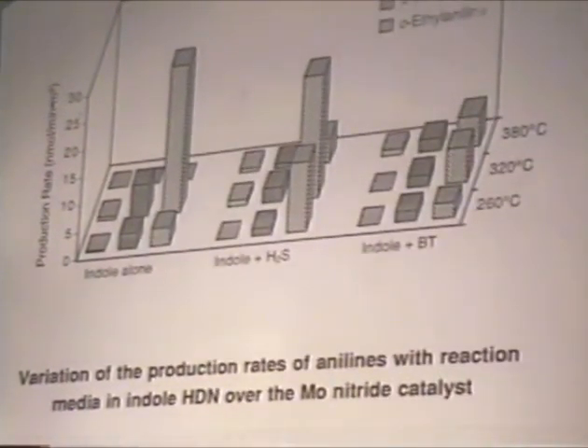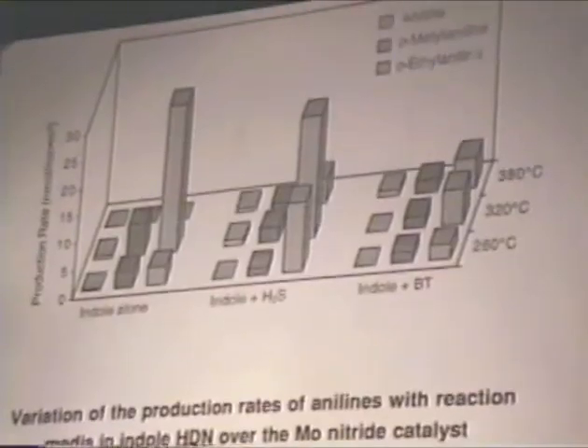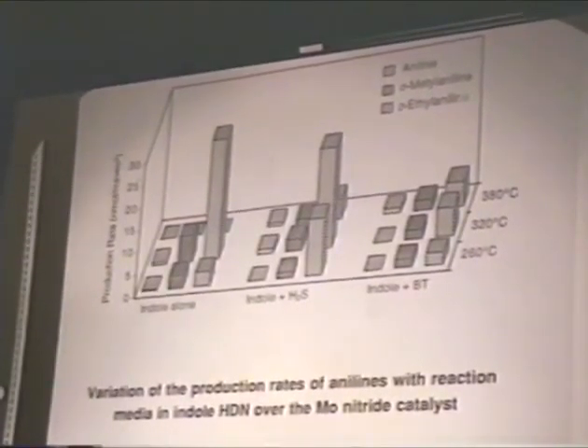Now, one last product distribution observation is, as I mentioned earlier, we have seen significant levels of aniline formation. The largest amount is ortho-ethyl aniline. However, we see that before the nitrogen is removed, there is some dealkylation because we also see non-negligible levels of ortho-methyl aniline and in some cases small amounts of aniline as well.